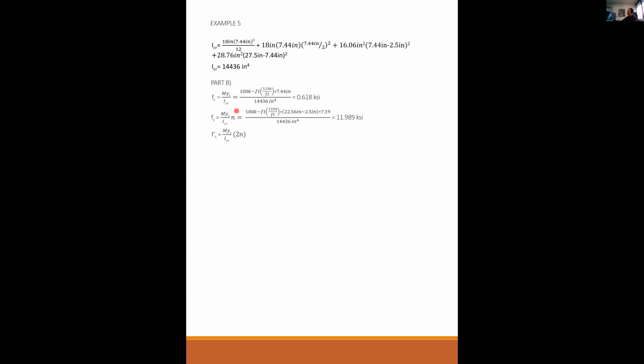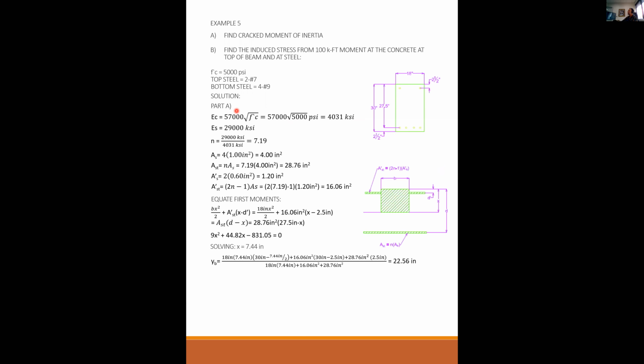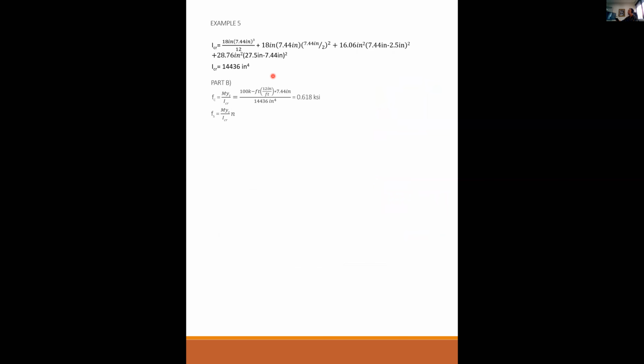So in this example, the strength of the concrete was 5,000 PSI. So 40% of that is going to be 2,000 PSI. And at the bottom here, we found that the stress in the concrete is only 618 PSI, well below 2,000. So that means that this method of calculating stress in the concrete and the 2 rows of steel is valid because the concrete stress is still in the elastic range. It's still less than about 40% of the final strength.